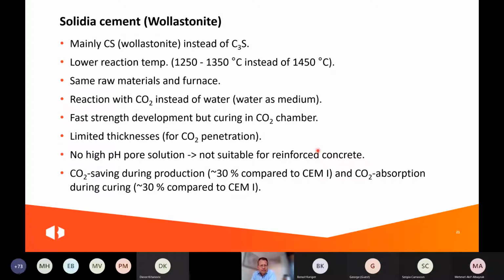So it reacts with CO2 instead of water. And interesting, you use the same raw materials and the same furnace as we have now. So it should be relatively easy to produce this product, but a bit difficult to process it into concrete. But the CO2 savings are quite high. You have 30% during production, mainly because you use much less calcium than with regular Portland cement, but you also have the CO2 absorption during the hardening, so that makes it really interesting.